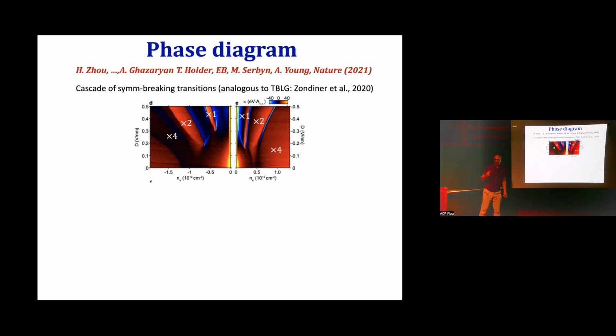This is a graphene system, so there's also a valley degree of freedom in addition to spin. And that symmetry between valleys, what we call valley K and valley K prime, is also spontaneously broken. What's shown here are the degeneracies of the Fermi surfaces. If you didn't have any symmetry breaking, every Fermi surface would be 4-fold degenerate because of 2 spins and 2 valleys. And you get these different phases where that symmetry is spontaneously broken. That's a phenomenon that seems similar to what we believe is also going on in twisted bilayer graphene.